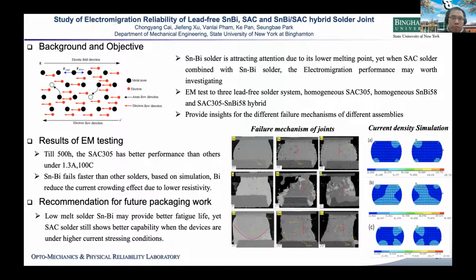We assembled three types of solder systems: homogeneous SAC305 as the control group, homogeneous tin bismuth, and a hybrid mixture of SAC305 components and tin bismuth paste, so we can provide insights into the different failure mechanisms. Up to 500 hours, as you can see from the figure, the first row, SAC305, still shows no failure with the progression of electromigration. In the second row, the tin bismuth, you can see a void forming inside the solder joints, and cracks forming at the anode and cathode sides. The hybrid joints also show failure, which is worse performance than the homogeneous SAC305.